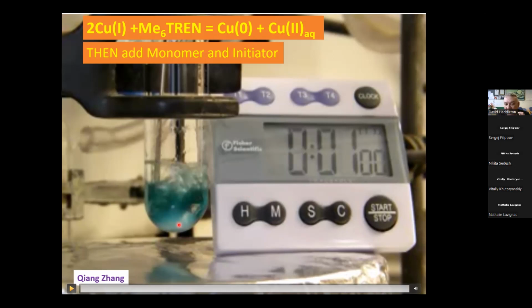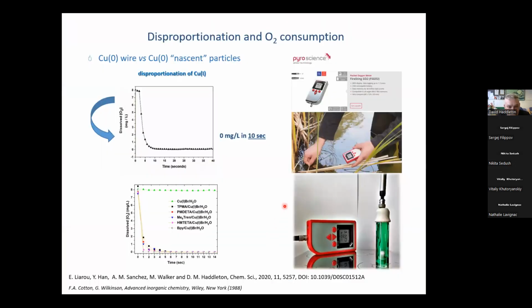If there's any oxygen, they get instantly oxidized back to copper 1. And that will instantly disproportionate back to copper 0. So your oxygen is actually consumed very fast. And at the time, we wanted to find a way to prove that.